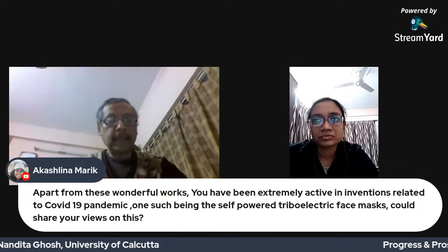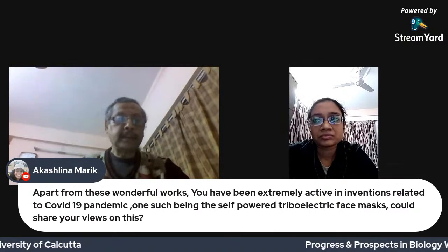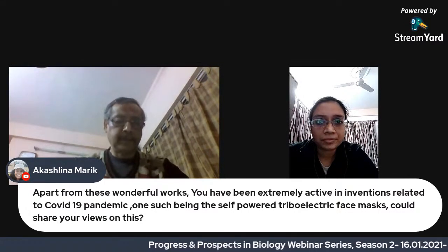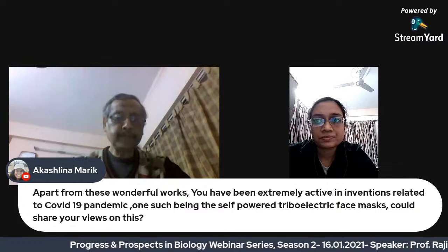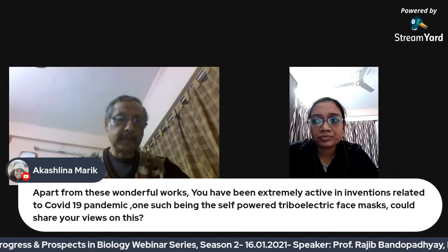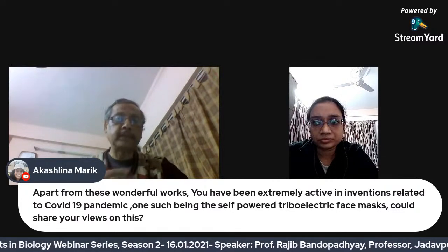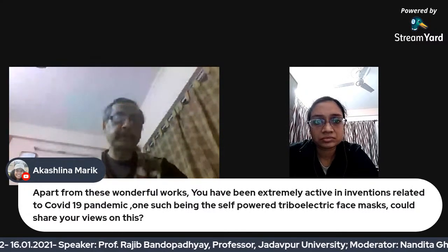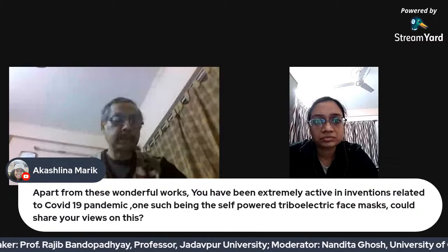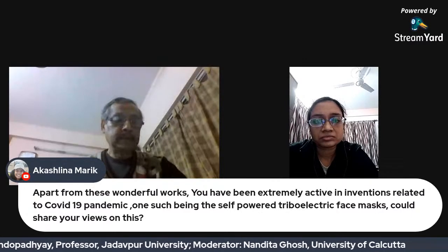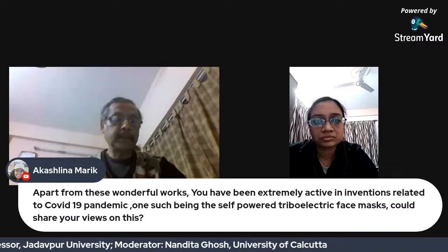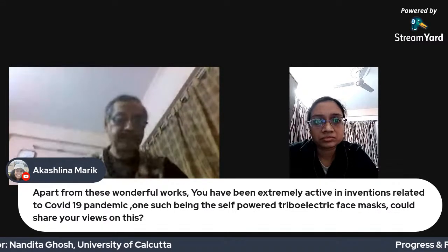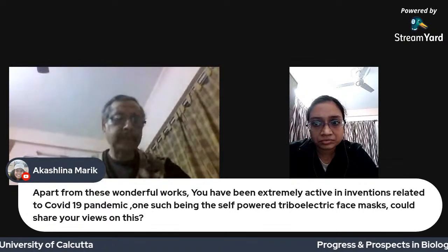So that was our idea. Okay, so based on that, we chose some triboelectric materials, and the idea is that there are two layers of triboelectric materials, and when we breathe or when we talk or when we sing, then there's the friction between the two layers, so that will generate some electricity. Now the problem is that since these materials are purely insulators, taking the charge out of it requires some expertise or some techniques.